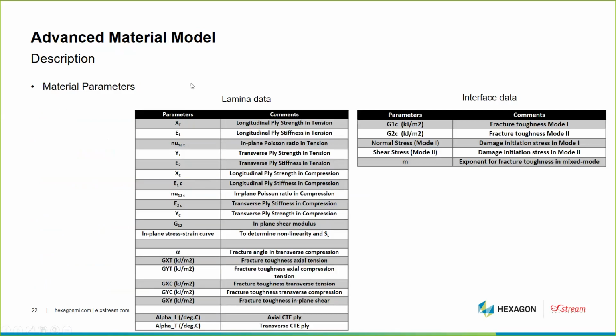So at the end, we end up with a list of material parameters. So typically we have here the lamina data. So we have the stiffness and strength, axial, transverse, tension, compression. So I would say this is typical data that we can find in the datasheet. And we need some additional parameters to handle the damage propagation, what we call here the fracture toughness in the ply, so intra-ply fracture toughness for the 4 modes, so axial, transverse, tension, compression.